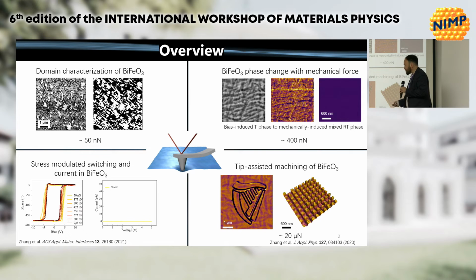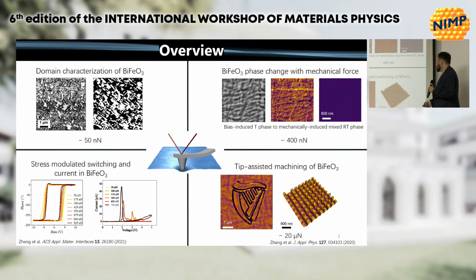And what happens when we measure the current during this? So initially there's no switching current that's detectable at this scale. From 50 nanonewtons on up, we start to see switching current. That switching current, in line with the change in the coercive bias, is going to lower and lower coercive biases, and the current peak is enhancing. So this is the thing that I'd like to talk about today.